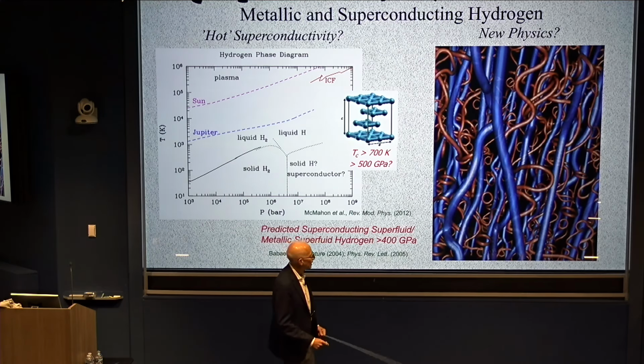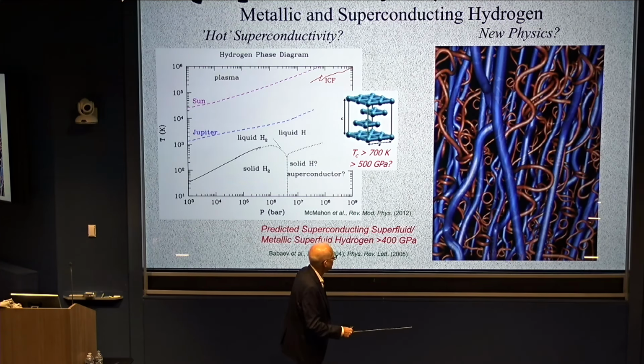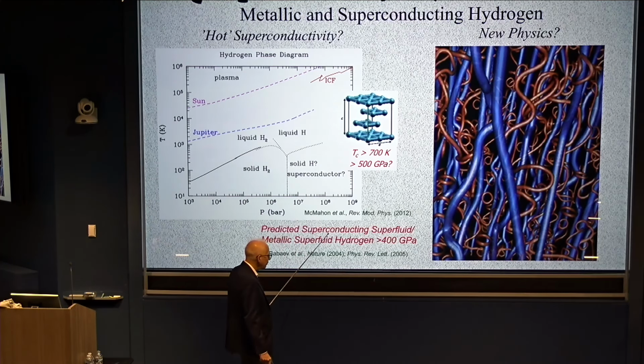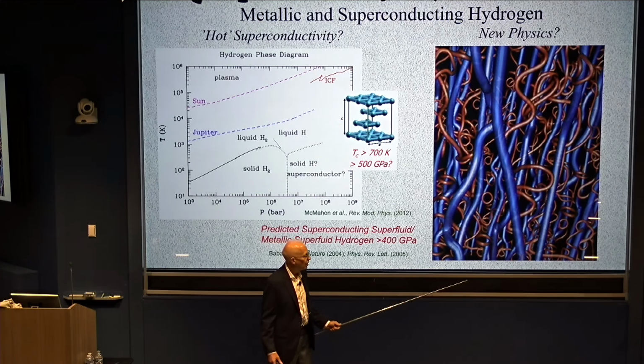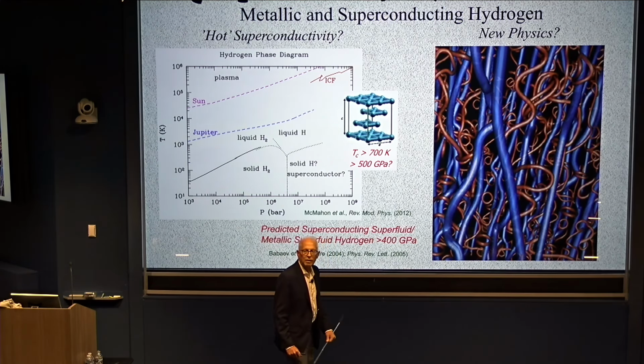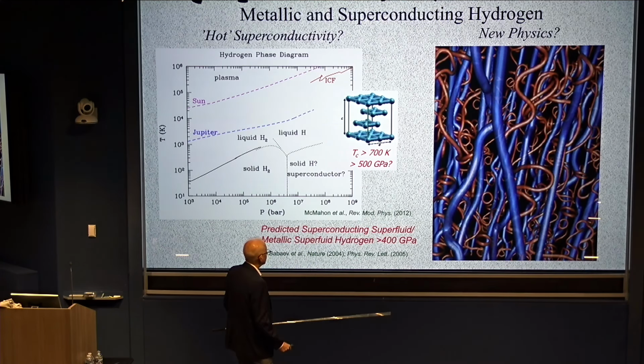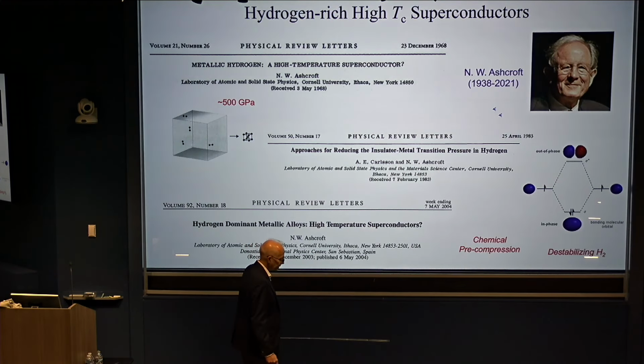But beyond this, and even more exciting, coming back to the work of Ashcroft and his colleagues, it's not just a superconductor, it could have some very, very interesting properties because of the light mass, the one proton, or deuteron, plus an electron gives you different spins, put them in a very high density state. You could have a superfluid that's metallic or a superfluid that's also superconducting. This would be an altogether new state of matter, but occurring at quite high pressures, above 400 gigapascals in their estimation, 4 megabars. But this is really a new state of matter altogether, one that simply has not been seen in any other element, clearly at ambient conditions. So it also has driven the development of a lot of what we're studying.